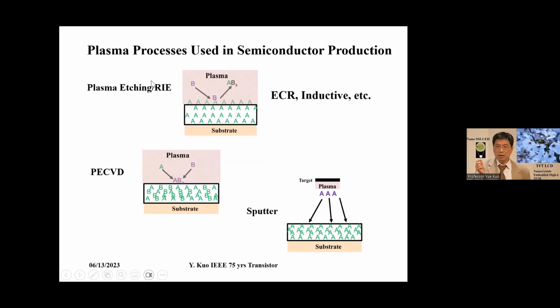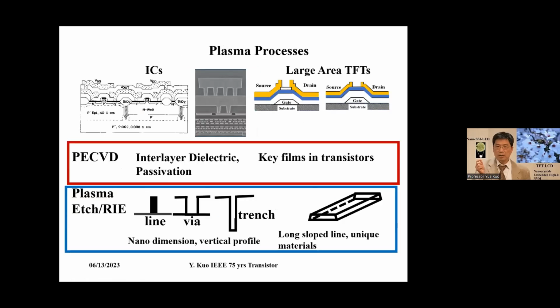So etching and deposition depend on the surface. If the plasma element reacts with the substrate and forms a volatile product, we call it etching. If the element from plasma reacts with the substrate surface and deposits, we call it plasma deposition. Those are the fundamental plasma processes with two electrodes. Then people use ECR and inductively coupled devices to introduce free radicals into the plasma phase to make the density of radicals higher, so as to enhance the deposition or etching. So that's the basic principle.